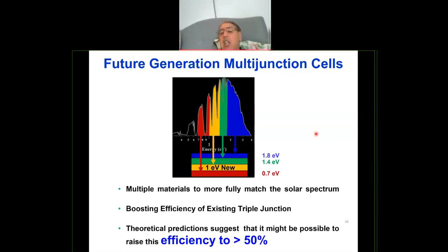So the challenge has always been how to find a compatible semiconductor to add to this 3-junction, which has a similar lattice constant to the 0.7, 1.4, and 1.8 eV materials. And this 1 EV, which is very important. So the prediction is, if you can find this 1 EV material, you should be able to improve the efficiency even higher, to 50%. So this is the idea.